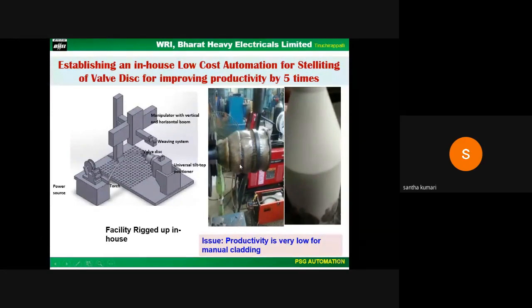Good wear resistance can be obtained due to the characteristics of chromium carbide dispersed in the matrix alloy that is deposited. These results showed a pore free, that is porosity free, coating without surface oxidation, and the required dilution was achieved with this process. We used the STT process. It was a well suited process for this application.